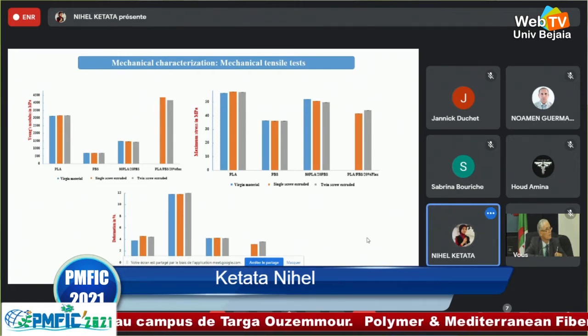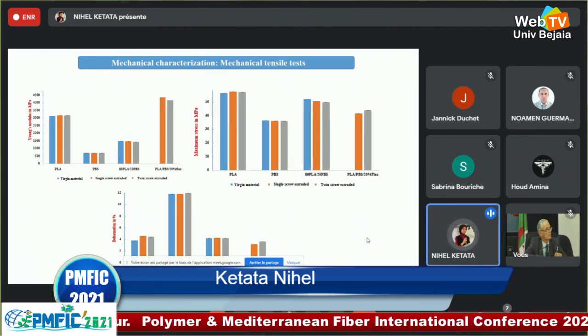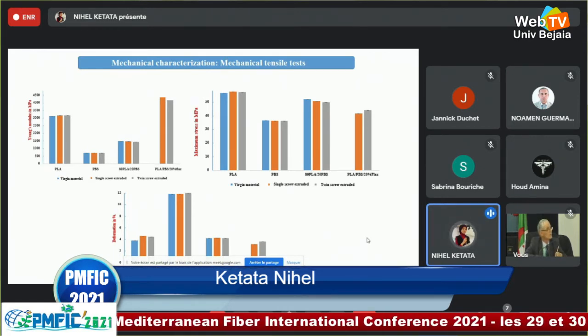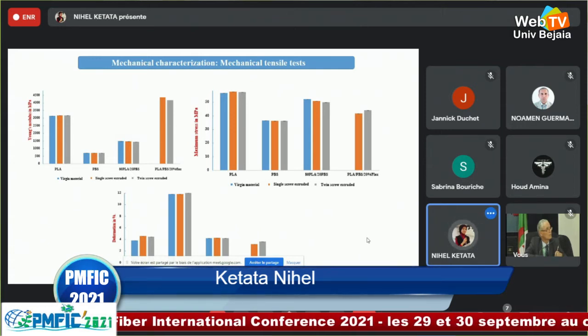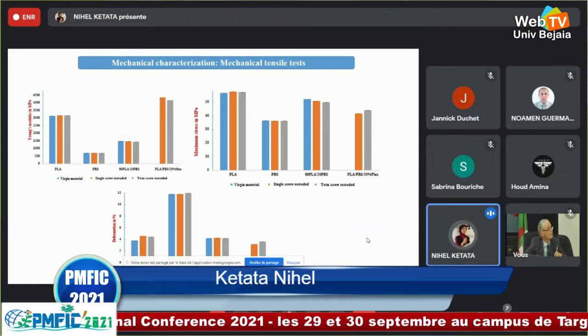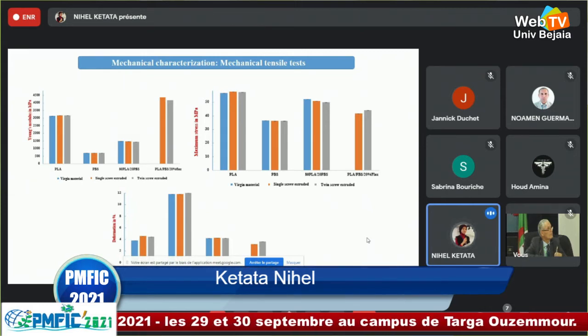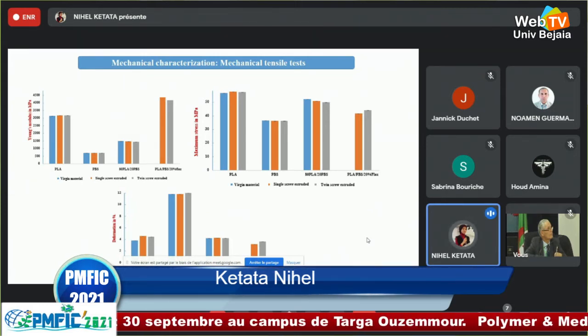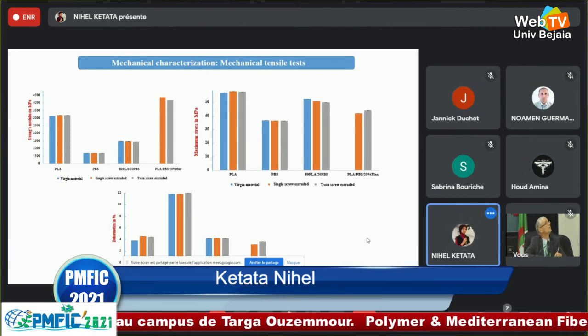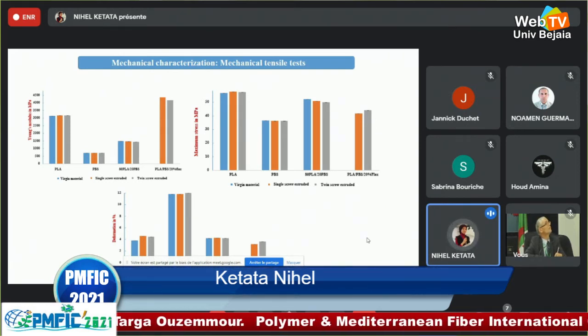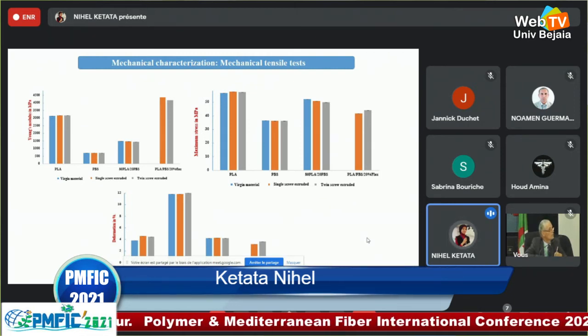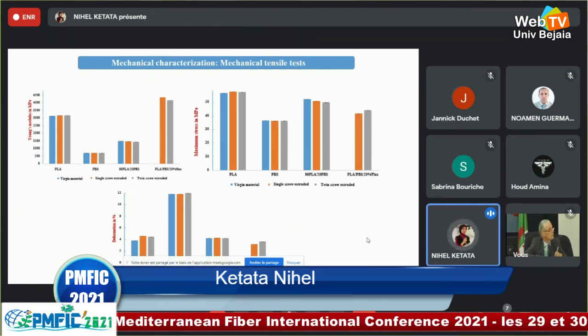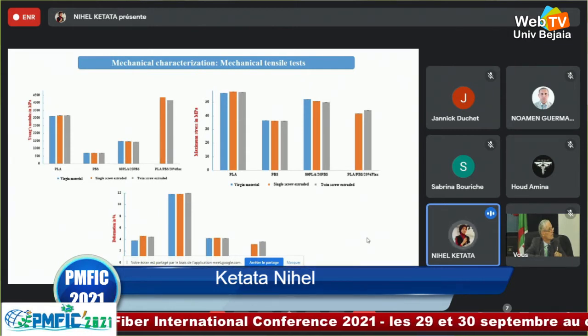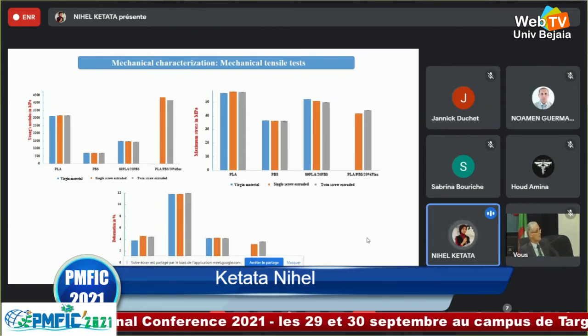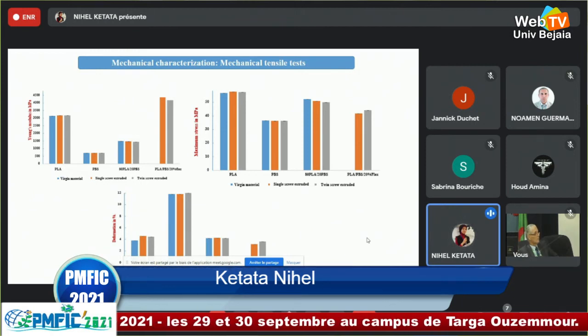For the maximum stress, we saw that the tensile stress of the composite is slightly increased in twin-screw extrusion compared to the single one. This is due to the good dispersion of the flax fiber in the matrix compared to single-screw extrusion. The tensile strength of the matrix of 80% PLA and 20% PBS without reinforcement is reduced after extrusion due to the high shear stress on the die.